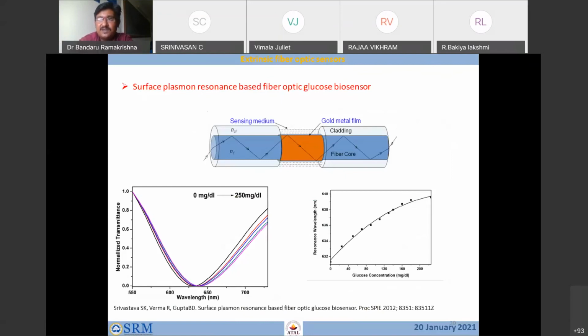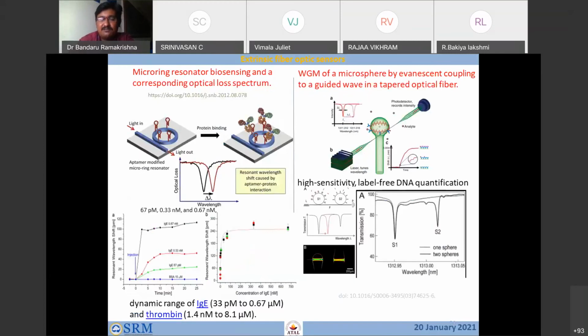People have tried that. This is the fiber coated with a thin film, and light is passed. Because of the gold presence, there is a particular absorption happening for the gold, and any environmental change around the gold gives a change in refractive index and then a change in the absorption characteristics of the gold. So now that can be recognized. People have also tried micro resonator rings and spheres. These ring resonators or sphere resonators resonate at a particular wavelength, and this resonant wavelength is sensitive to environmental change. If any particle comes and binds to the micro ring resonator or sphere resonator, you get to see a slight variation in the wavelength shift.